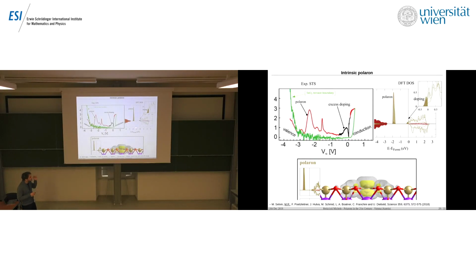And if we consider the same with density functional theory, we have the polaronic state, and then we add more electrons, and we also obtain that the more electrons we put, the more they form a dispersed gas which occupies the bottom of the conduction band.